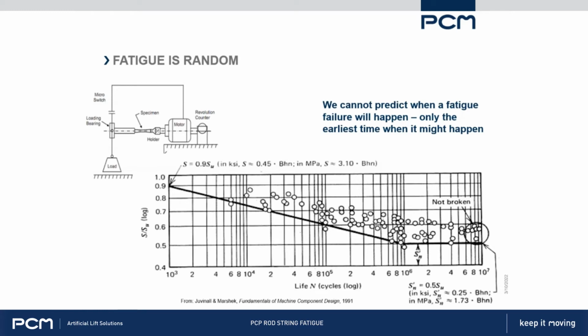So we can't predict exactly when a failure is going to happen, but if we use this black line, which is drawn on the left side of this cloud of points, then we can get a good estimate of what the earliest possible time to failure is. Now, the other thing to take note here is, again, there's no torque, no axial load. This is just pure bending in this. Well, it's not pure bending, there's some shear as well, but it's basically just a bending load.